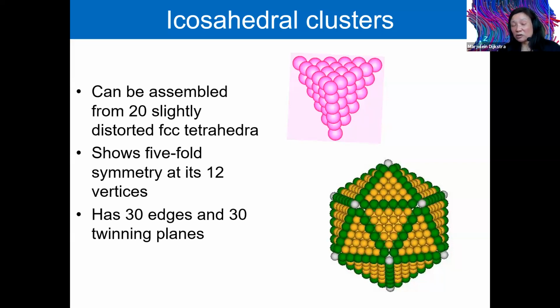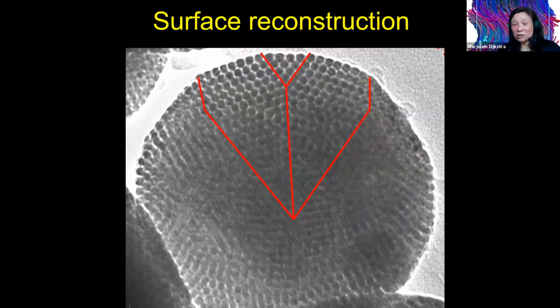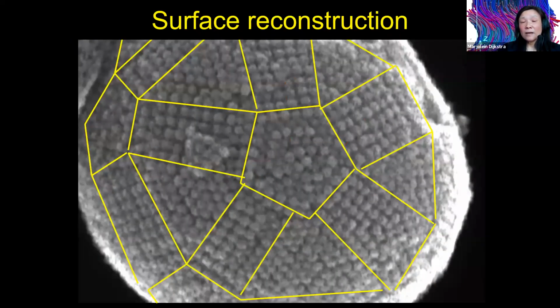If the particle is bigger, so it likes to grow further, then you will have all these tetrahedral domains, 20 of them. An HCP plane is grown on top of these tetrahedral domains, and then another FCC domain is formed on top of these tetrahedral domains. And these triangular wedges are just filled with another FCC unit. And then the outside looks as follows. There's this five-fold symmetry in the middle. There are these 100 planes, and then there are these 111 triangular facets also at the outside.